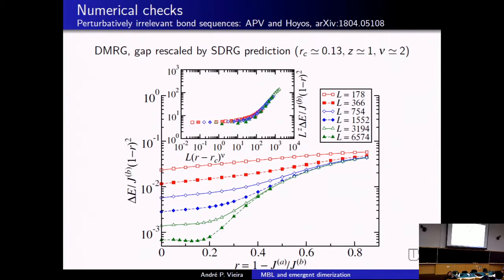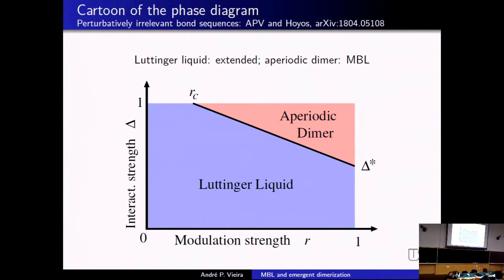So this leads us to believe that this whole phase here is many-body localized, and we also did SDRG calculations outside the Heisenberg limit and obtained the result that there is a minimum value of the anisotropy in order to produce this aperiodic dimer many-body localized phase, separated from the extended Luttinger liquid phase.